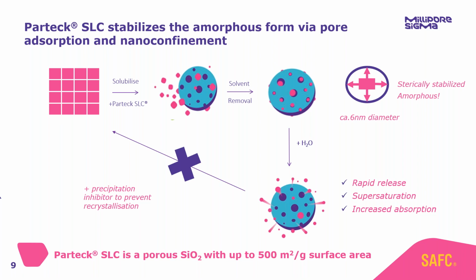We can then remove the solvent rapidly, and then what we are left with is the individual drug molecules confined within that porous network. And because we're talking about a 6 nanometer pore, what we essentially have is a sterically stabilized amorphous formulation. And some really interesting physical chemistry takes place on this scale, and we're going to cover that in the next section. But we have a sterically stabilized amorphous formulation. This powder can then be combined with a standard blend and tableted or filled into a capsule.